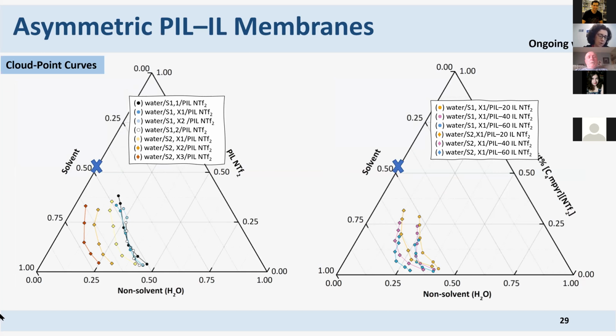Here are our binodal curves for two solvents. We did this for two solvents. This is for solvent 1 and this is for solvent 2. So for solvent 1, we have different compositions. They are both mixtures of solvents, and we can see that they are different. Of course, what we want is to have as high as possible a two-phase region.